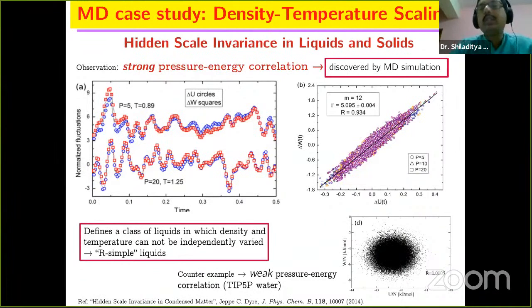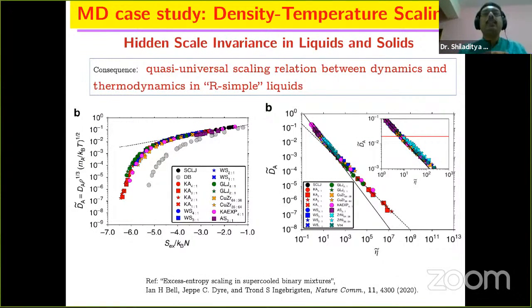There is a concept of isomorphism, which is beyond the scope of today's talk. But the point is that I will just mention a couple of consequences which came fairly recently, like this year, of this kind of hidden scaling invariance in liquids. If you measure a dynamical quantity and a thermodynamical quantity, then you expect some kind of quasi-universal scaling, which is shown here. On the y-axis I plot the diffusion coefficient, measured in units of density and temperature, and on the x-axis we have the entropy. And you see that for a wide range of different systems, they have a master curve.